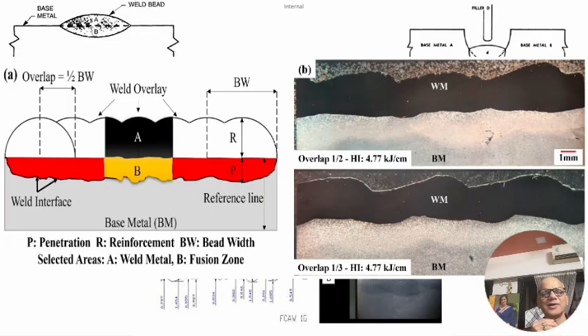As you see in this slide now, for the number of layers, the overlap has been shown as half of the bead width, which in turn comes to about 50% here, and then the rest everything is going to see it. But another important parameter which I want to show here is this red and yellow portion. They are our penetration side, and the penetration should be as uniform as possible, as shown here. Still there are a few areas like this P here which is larger, here it is lesser, and this is something which will give us trouble in our bend test.